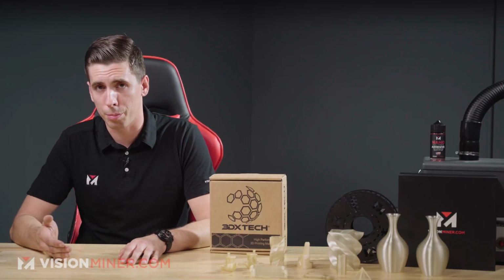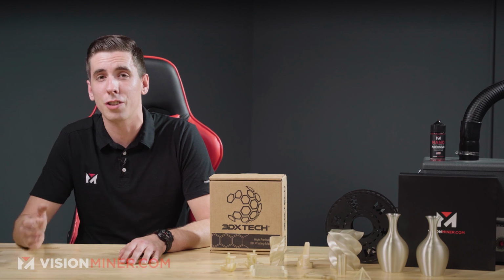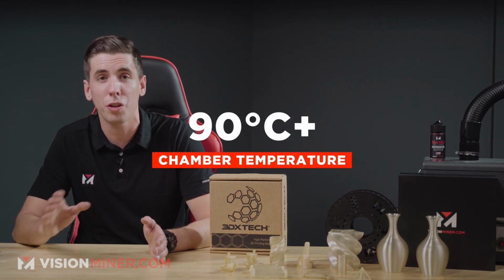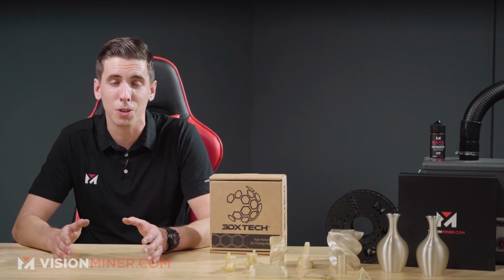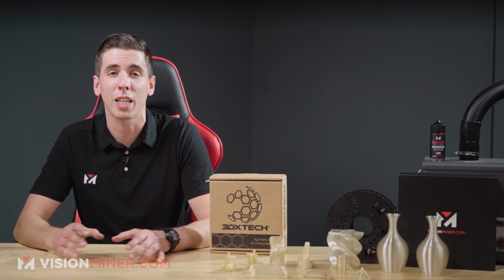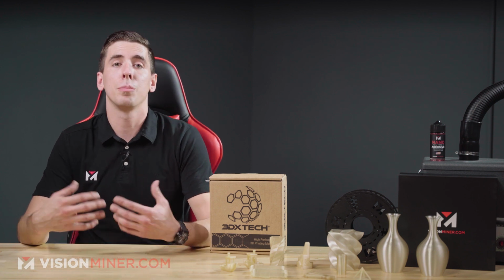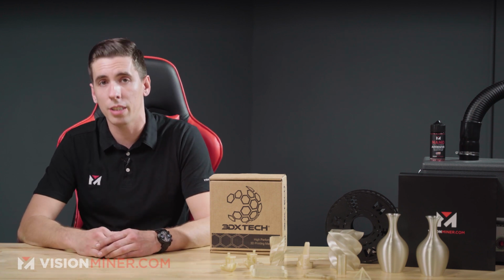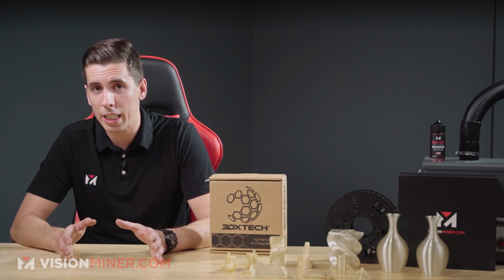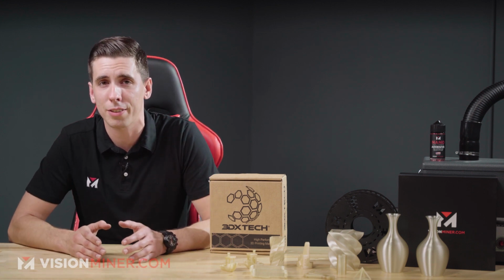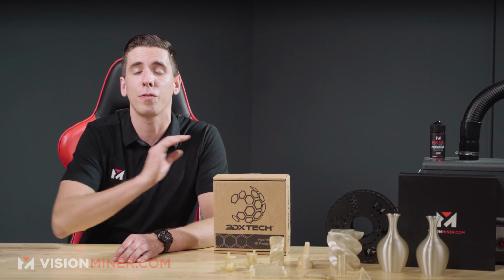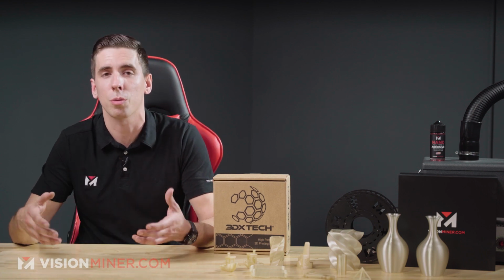As far as chamber temperatures go, you do want to have a heated chamber. 90 Celsius or more, the better. This stuff loves to warp, so the closer you can get to the glass transition point of the material, the better results you're going to have. Now, you can get great results in 90 Celsius or above. We've done a lot of crazy projects, but as new machines come out, it is something you'll want to consider. Now, as for drying the filament, yes, like almost every other plastic, you gotta thoroughly dry this stuff before you process it, which is the fancy word for melting.